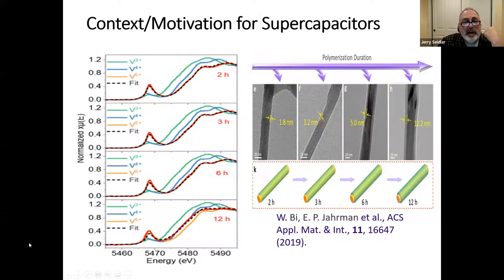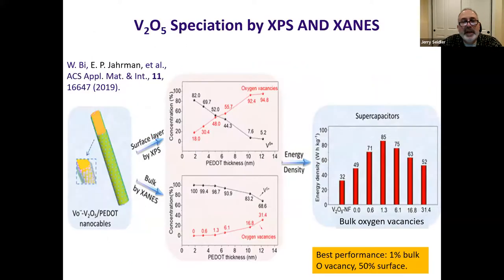So in the lab, we measured a number of materials with different durations and thickness of the polymer coating. And you can see that this vanadium 5+ pre-edge peak is changing with the effort with which one puts into introducing oxygen defects. And that makes perfect sense. And so from the XANES, we would infer that the vanadium 5+ comes down about a third when you have the largest thickness of this polymer that's inducing the oxygen defects.